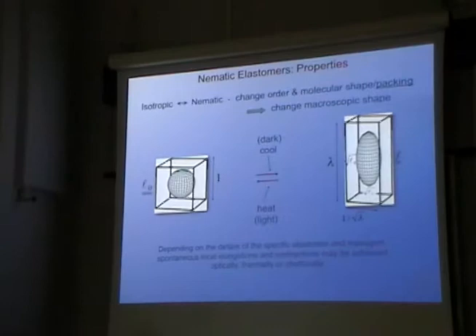The degree to which the polymer is affected by the liquid crystal must have something to do with the order parameter — how lined up it is with the liquid crystal. The more lined up it is, the more elongation you have in the direction of the liquid crystal. There's this beautiful system by Finkelmann where there's a thin long strip of nematic rubber being heated and cooled. When heated, the order parameter goes down — they start out long and retract. When cooled again, they extend. It lifts a weight up and back down just as a function of temperature. This is a bulk elastic effect purely driven by the nematic properties.